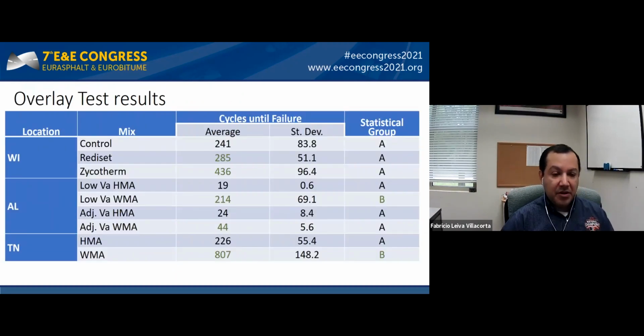Another result that we wanted to show are the overlay test results. And again, I'm showing three projects. In total, we have five. I'll show the next in the next slide. But you can see that in most cases, the results of warm mix technologies showed higher cycles until failure, which is showing that warm mix technologies are better performing mixes compared to the hot mix companions.